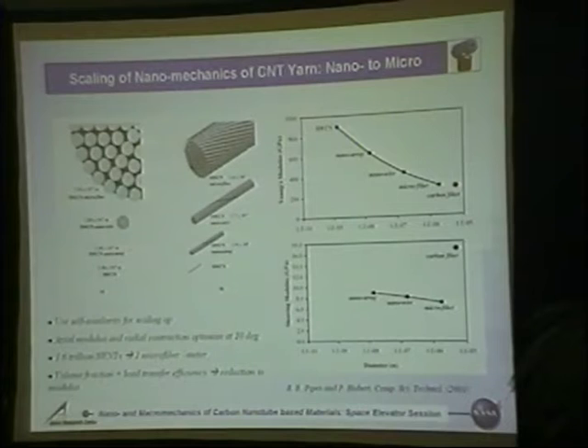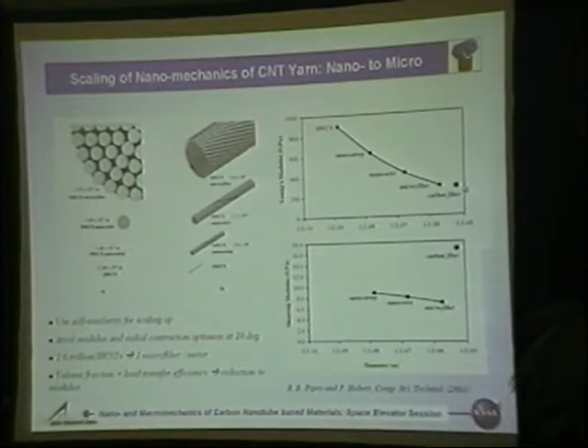But then the problem is when you go from there, you look at this graph. This is single wall nanotube and it has degraded by that much. So this is bad news, but it's not so bad, because this model is a simplistic model coming from continuum theory. It has a lot of assumptions and approximation. When we come to microfiber, here's microfiber. It's kind of carbon fiber. In carbon fiber, you're already making them, right? So what's the degree? That shows.